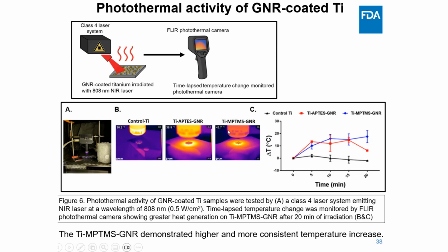As shown here, the titanium coated with gold nanorods via MPTMS exhibits a more consistent and higher temperature rise, about 15 degrees after 20 minutes, compared to the APTES coated surfaces, which were not that consistent, and plateaued and went down after 20 minutes. So this suggests more effective photothermal conversion, likely due to the denser and more stable gold nanorod attachment on the MPTMS treated surface. So we are not only seeing better coating efficiency, but also improved functional performance here.